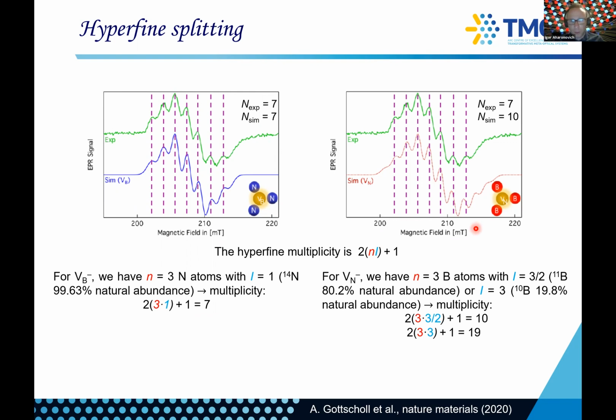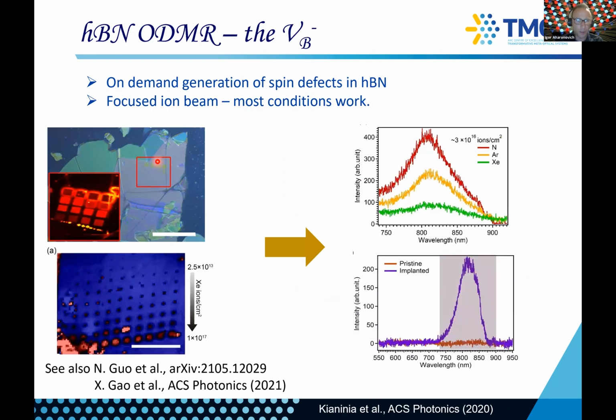There are a bit more details about the symmetry, how we figured out that it's a D3h symmetry, again from EPR. So now that you know for sure you have a boron vacancy defect, it's easy to make those defects on demand. We just took a flake and, as I mentioned, irradiated with different ions, and you can see that we could make an array. And there, indeed, you can see this emission changes as a function of the ion. Intuitively, xenon is very big, so it will make very big damage. Therefore, the emission is not that great. But nitrogen is obviously a very small ion, so it will knock off maybe potentially 1 boron atom, and you will have a much better emission creation here.